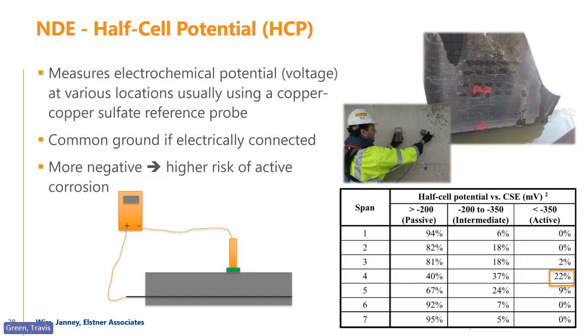If you guys haven't seen it, it's literally a voltmeter and a copper sulfate reference probe. So you see me here, frankly, a long time ago with a voltmeter and a little probe. They're connected, right? One lead goes to an attachment onto the rebar, and the other, this little sponge with the reference anode, gets moved around, right? And you can see the little dots from the water on this pier at Nottoway, right? And so then we're plotting these to show whether we think there's ongoing corrosion. It doesn't show the corrosion rate, but it gives you an indication of whether there is ongoing corrosion.